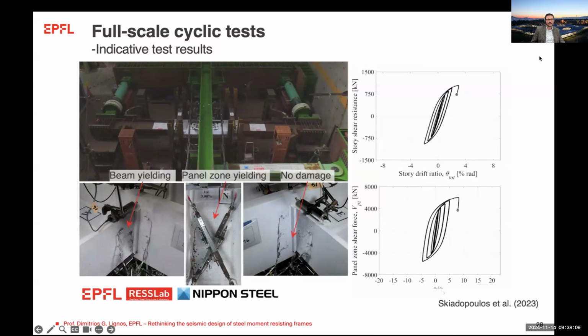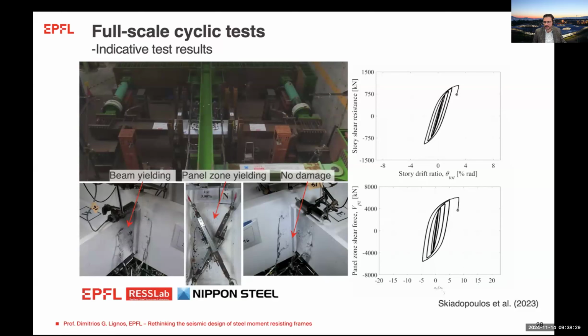So what you see here is that the story shear resistance of the entire subassembly at 2% drift doesn't exhibit any degradation. And besides panel zone yielding, which reached about 6 gamma Y in this case, there was only minor yielding in the beam flanges. But if you inspect here the region near the connections, you see that essentially the connection doesn't exhibit any serious damage that you would worry to repair.